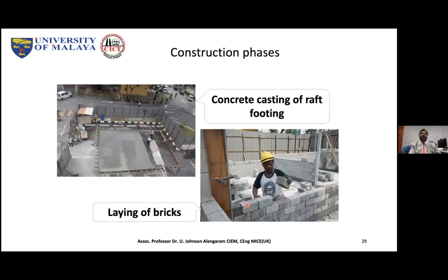Once we were given the task of this car park area, you see the building here. This is the car park area. It was a car park, so we had to use it. We did the raft footing. The aggregates that we used here were 100% slag aggregate, heavyweight aggregates. For the cement, we reduced 15% of the cement using palm oil clinker powder. We manufactured this block using steel slag aggregate and also oil palm clinker aggregate. These blocks are sustainable blocks.